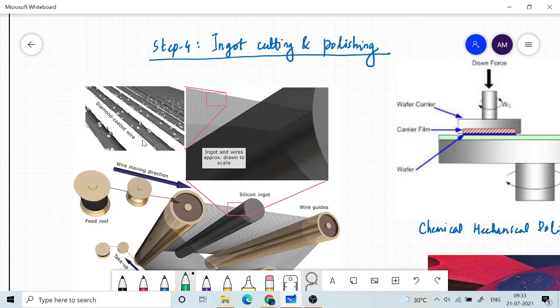But there is a problem if you keep the thickness so low, that is the mechanical stability. When you hold the wafer, it will wobble. So in order to avoid that, some minimum mechanical strength should be ensured. Therefore that is what decides it, and it also depends upon the diameter of the wafer. If it is a smaller diameter wafer, you can have less than 0.5 millimeter thickness.